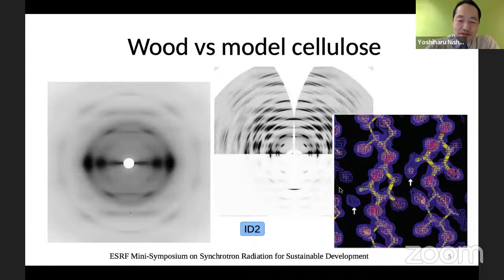When we align those nanocrystals, we can get fiber diffraction. This is the fiber diffraction in the middle, taken from this tunicate cellulose. Compared to the left, this is what we get if you just shoot a stick of wood with an X-ray beam. We get a fiber pattern, but the peaks are blurred, and the information we can get is much less. So from these large crystals that we can obtain from tunicate, we can do standard crystallography to locate atoms inside the crystals. This was done about 20 years ago at ID2.